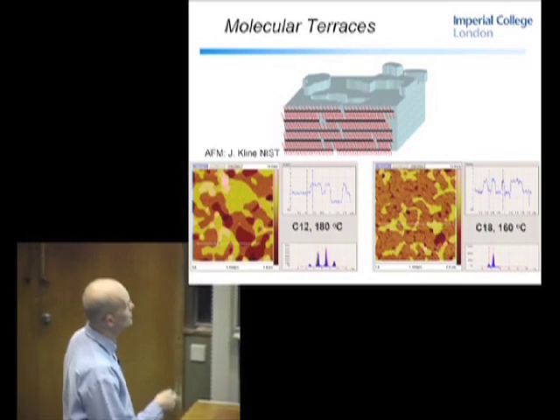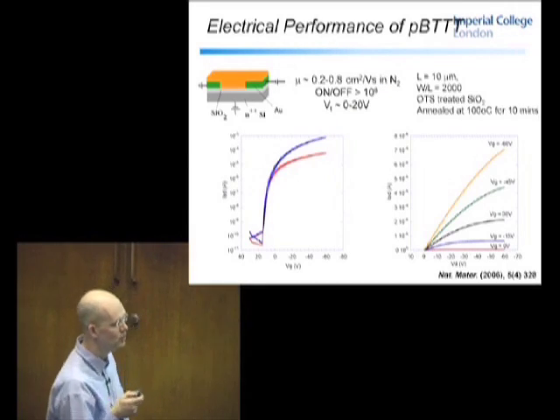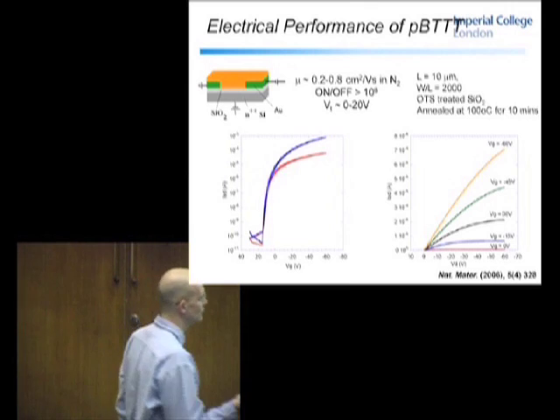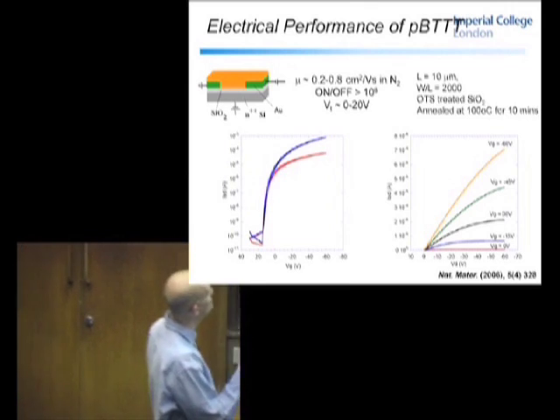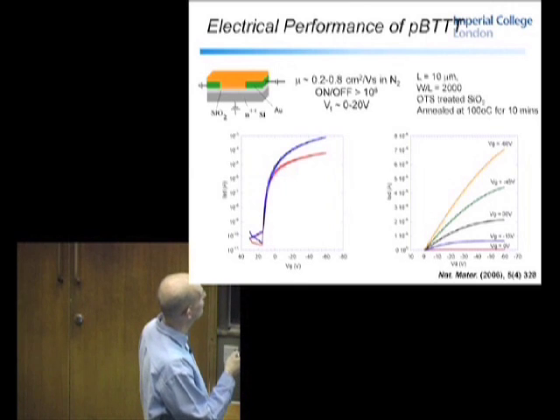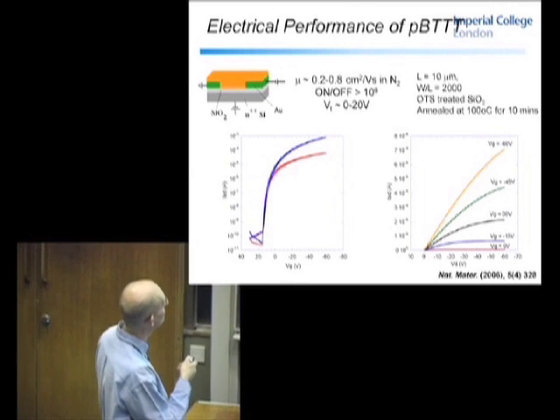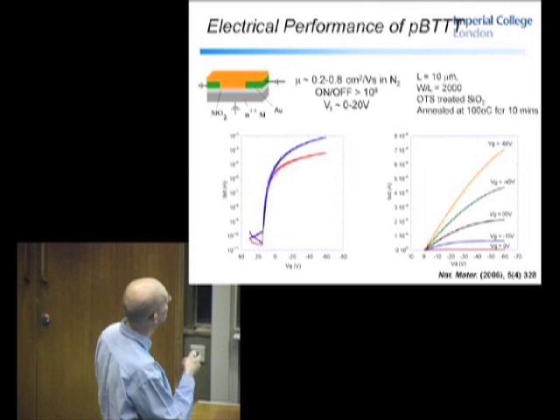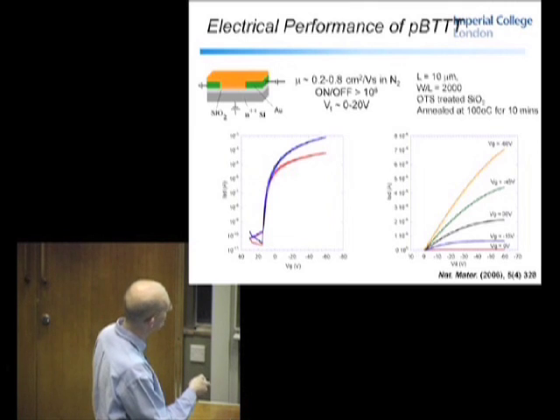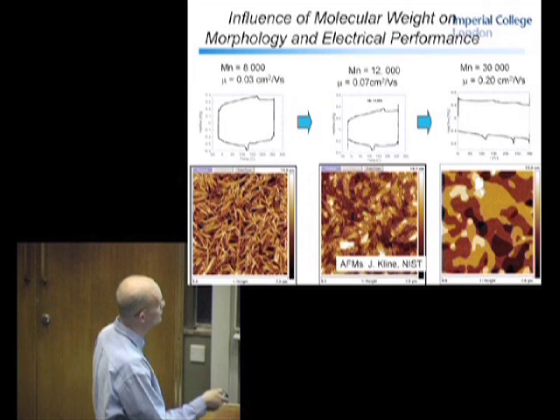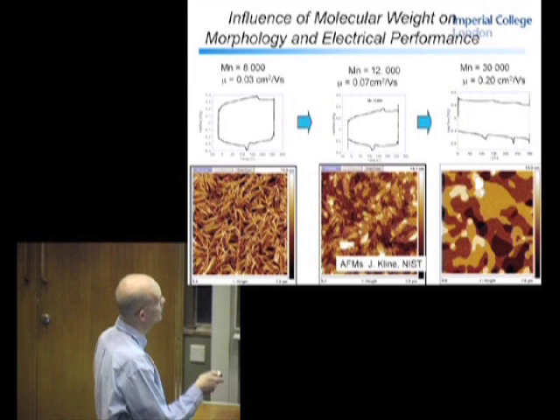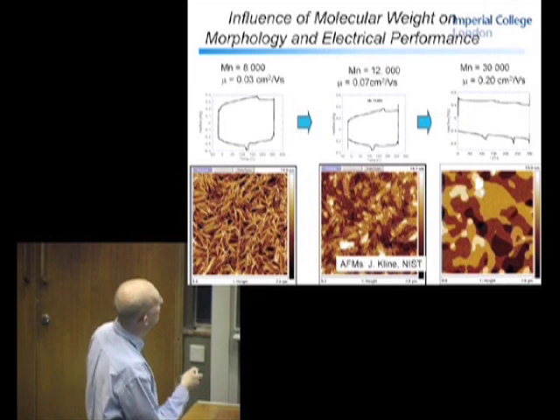So, well, all this is almost esoteric. I guess we were looking to try and make transistor devices. So what's the electrical performance like? And again, we're able to achieve very high mobilities. This is a bottom gate device, so silicon, silicon oxide, gold electrodes. Typically we have HMDS or OTS treatment, again to promote the organisation of the semiconductor. And we get these nice transfer characteristics, good output characteristics as well, and the details are shown here.